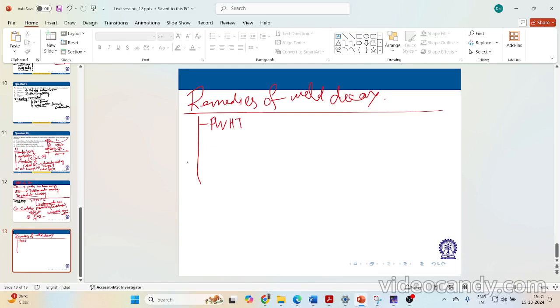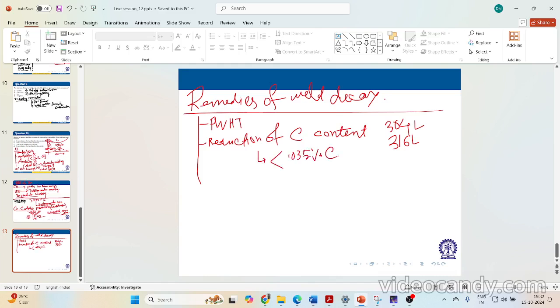Then, you can reduce your carbon content. The low carbon grades, like 304L and 316L, are low carbon grades of stainless steel. They are designed to have less than 0.035% carbon, to reduce the susceptibility to weld decay.